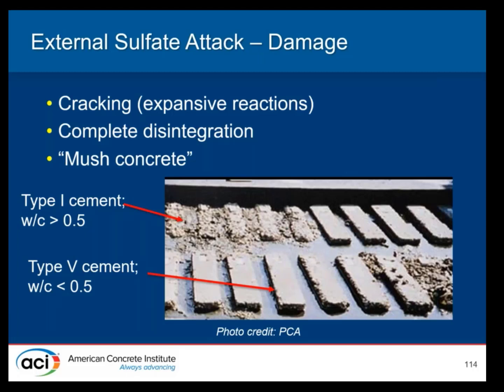So the deterioration of the concrete results in basically complete disintegration of the concrete. All your paste breaks apart and you've got nothing left but a pile of aggregates. It turns to mush. The rate of reaction is a function of how much sulfate is present, how much water is present, and then ambient temperature and humidity, and then the concentration and the type of sulfate that's present.